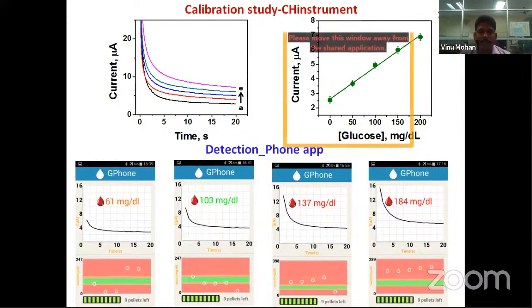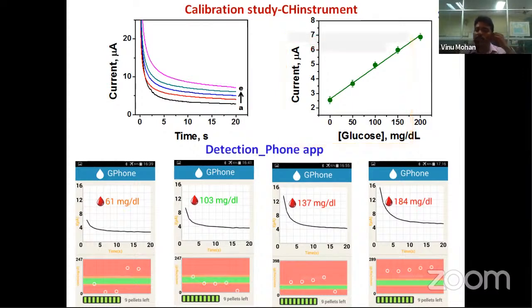As you can see here, we developed an Android-based app, and when we expose different concentrations of glucose to the electrochemical sensor, when we put 60, we got 61 milligram per dL. When we apply 100, we got 103. Very mild variation. For 190, it showed 184 milligram per dL.